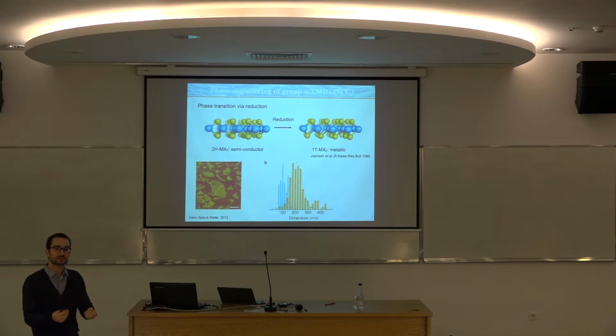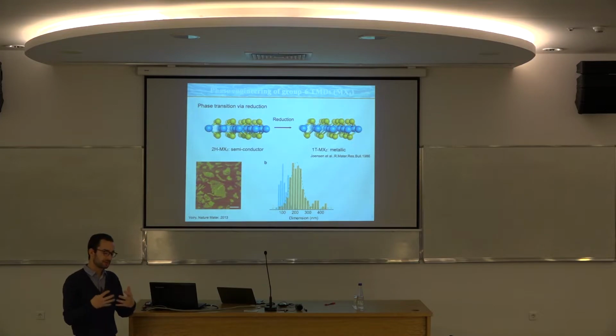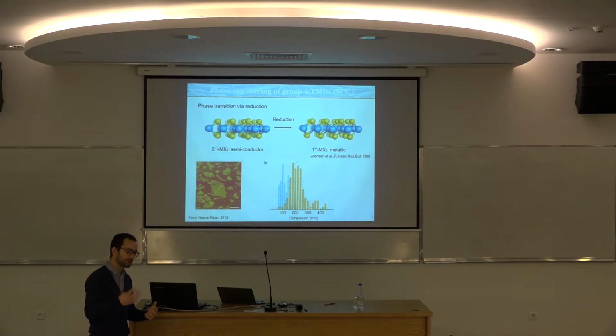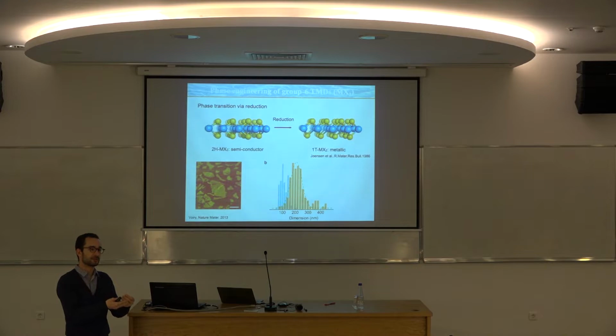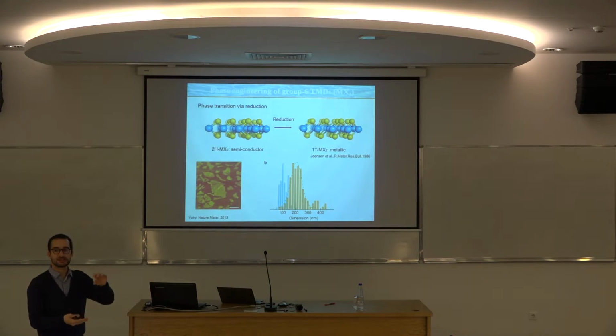And with this reducing agent, there will be electrochemical reactions. The butyl lithium will give one electron to the MoS2, and so you have to compensate the charge, so the lithium will intercalate at the same time. So you charge the nanosheets negatively, and you intercalate the lithium cation. So this is how it works,